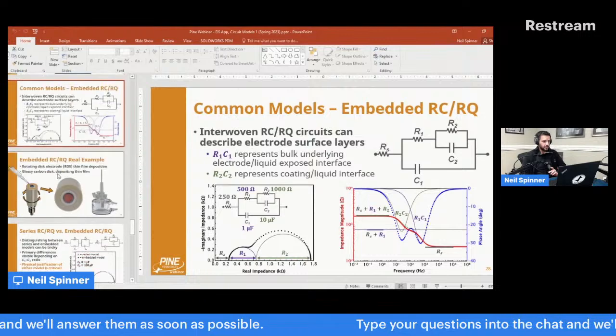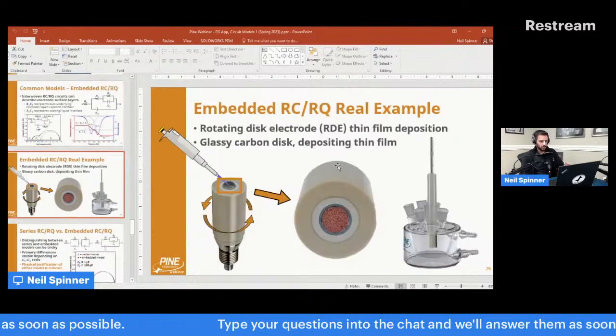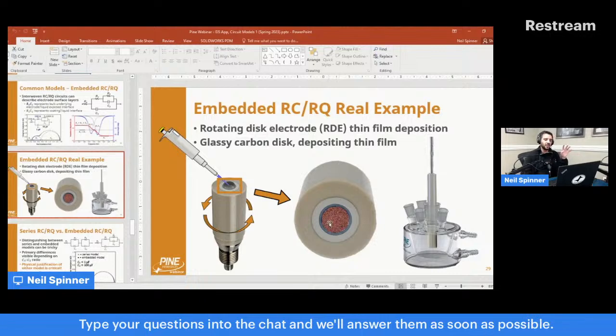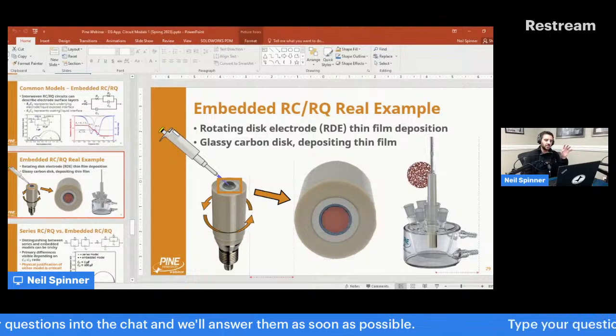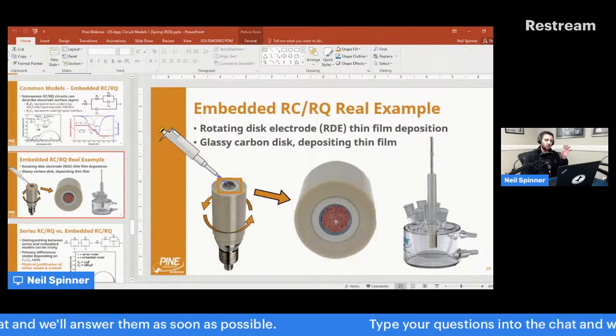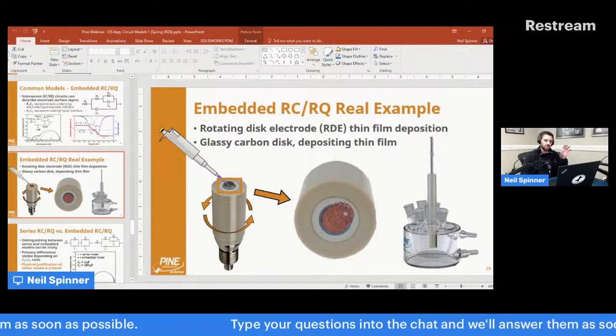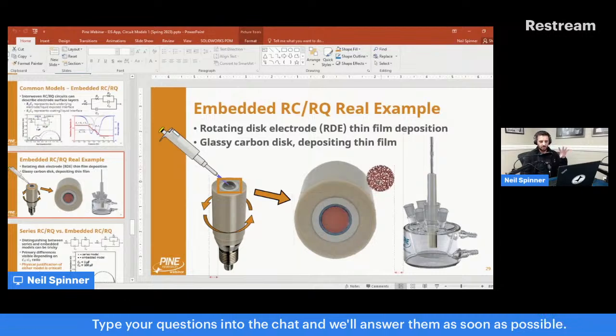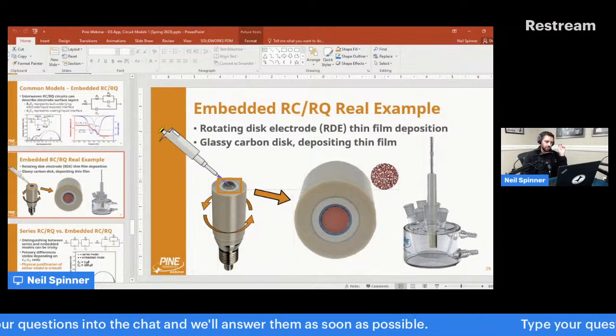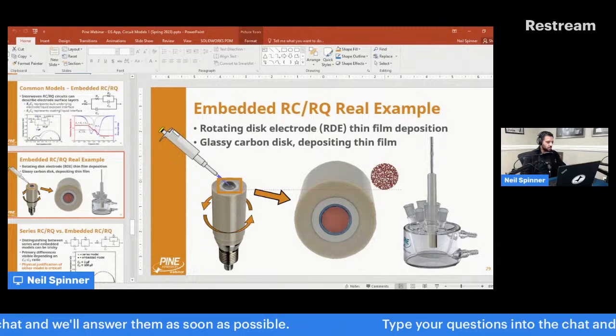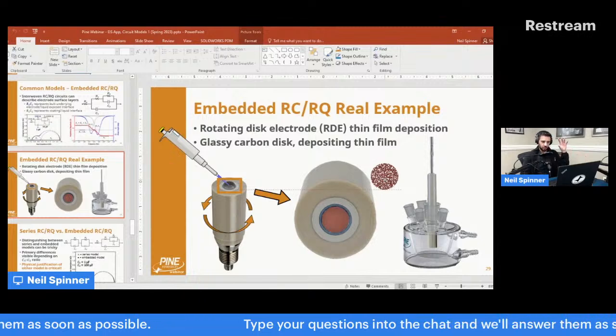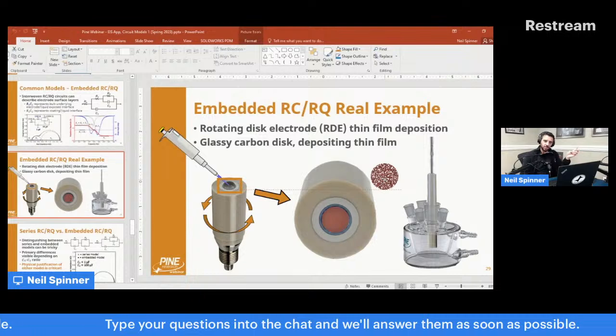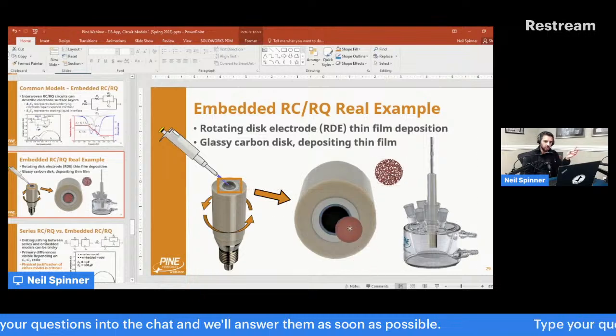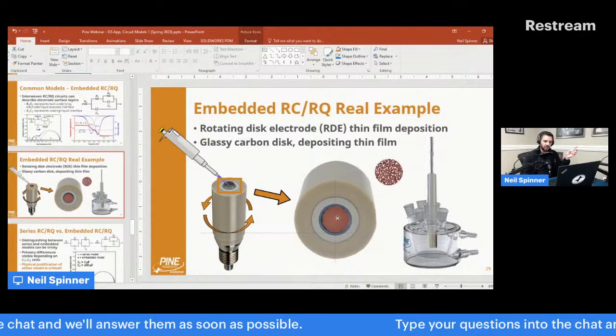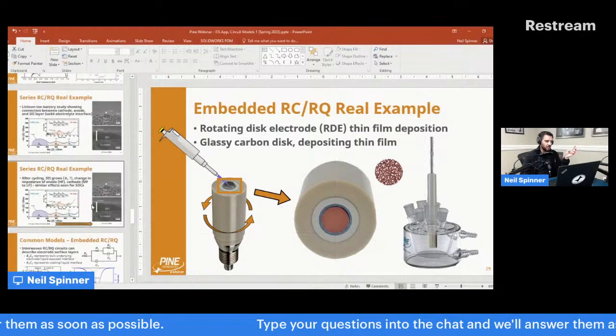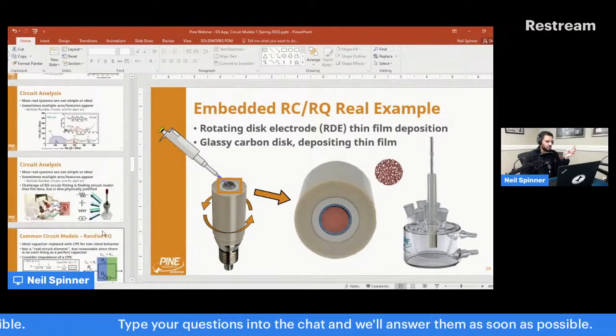The determining factor is whether this film fully covers the surface or the substrate is partially exposed. So you see the difference between these. I'm not going to do the whole animation here. The point is that it's similar to that whole process I just talked about: dropping a bit of your catalyst onto a glassy carbon, right? If you drop your film and it's fully covering it, then it's like what I have.